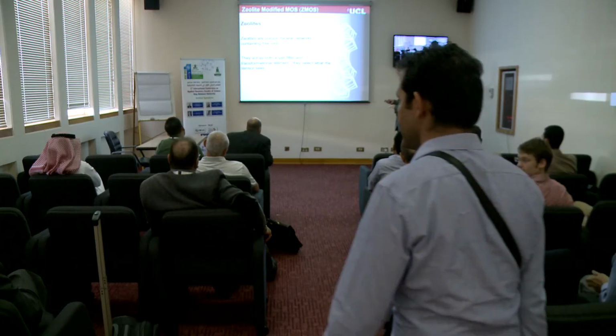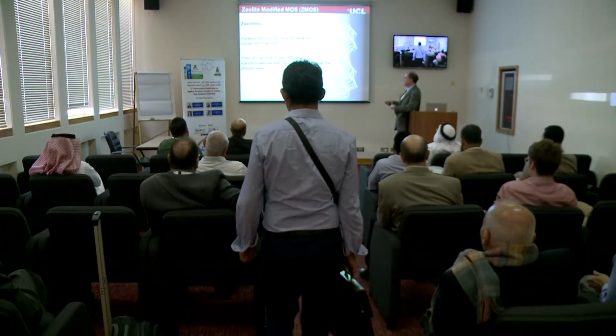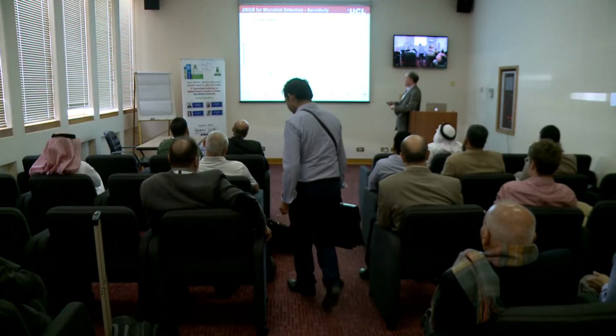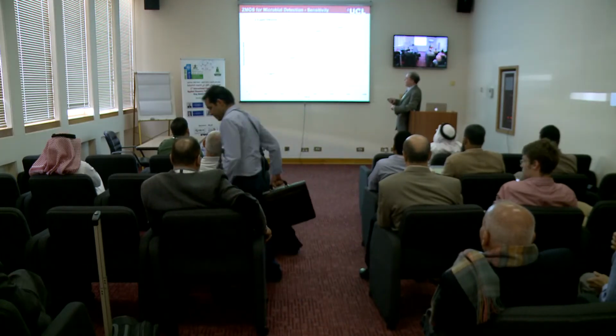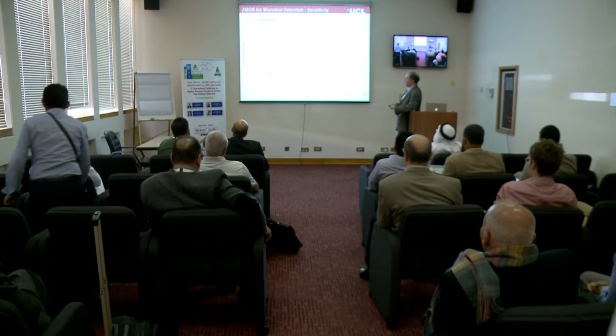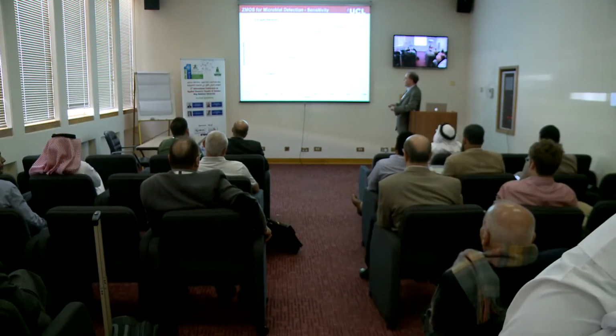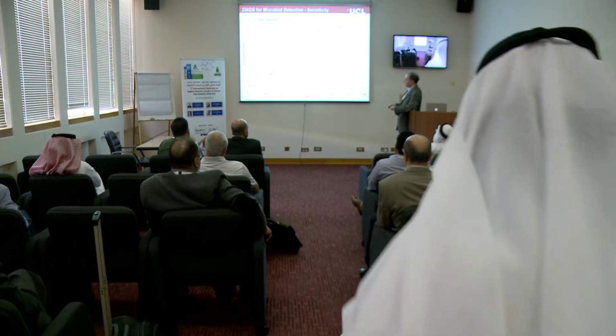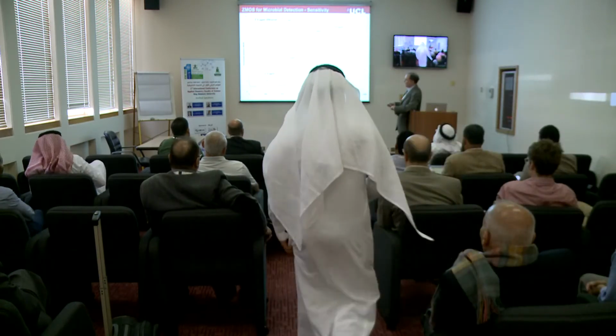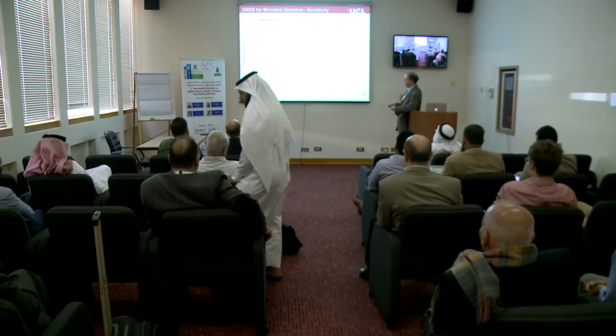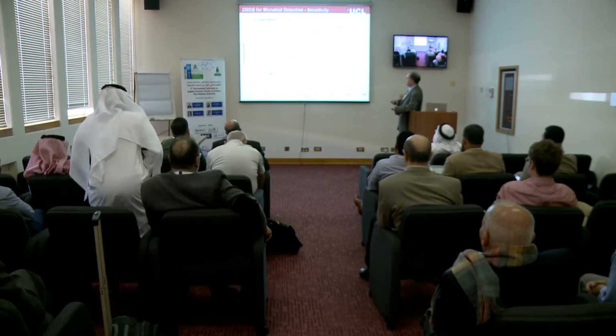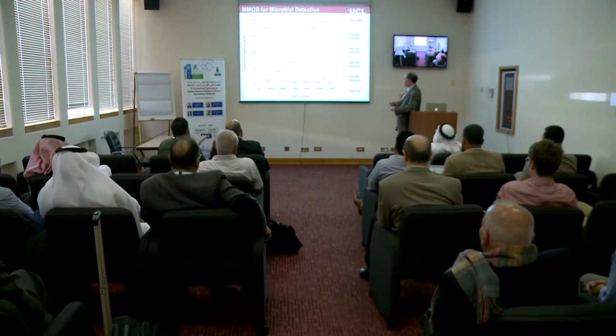And if we put a layer of zeolite on the top, they can give us gas filtration and also improve sensitivity. And this just shows some of the results related to ethanol, where we can see quite easily around 2 parts per million of ethanol with a pulse. So this is where we pulse the ethanol in. You can see a change in resistance. You turn the ethanol off, it returns to the baseline. And you get a pulse which is proportional to the concentration of ethanol.